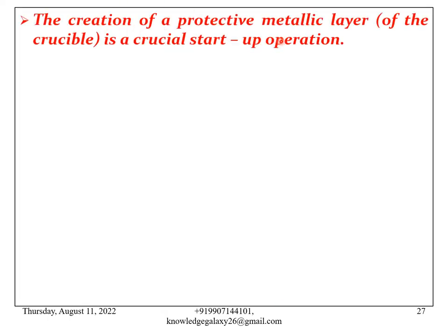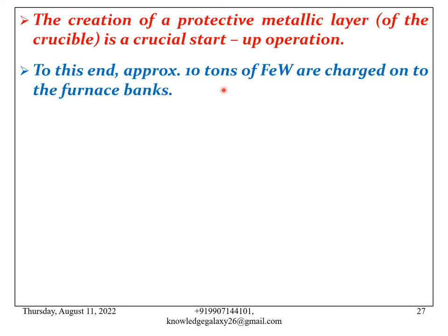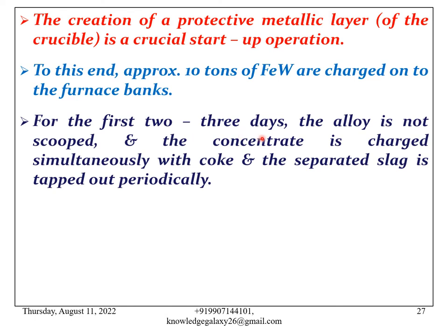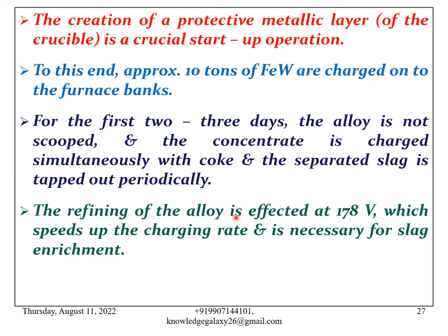The creation of a protective metallic layer of the crucible is a crucial startup operation. To this end, approximately 10 tons of ferrotungsten are charged onto the furnace banks. For the first 2 to 3 days, the alloy is not scooped and the concentrate is charged simultaneously with coke, and the separated slag is tapped out periodically. The refining of the alloy is effected at 178 volt, which speeds up the charging rate and is necessary for slag enrichment.